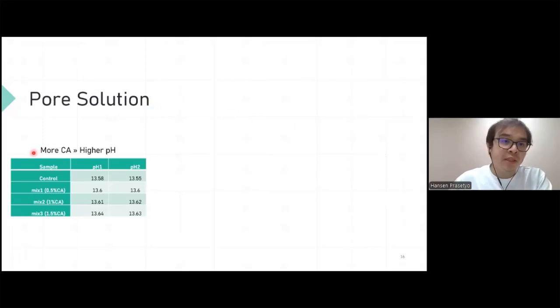And from a pH test, it shows here that when we add more CA, there's a slight increase in pH, which is small, but it's good because a higher alkalinity can help preserve the passivity of the steel rebar.